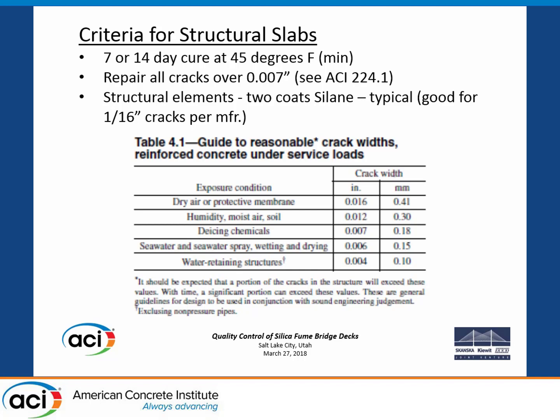So, can we just put silane on everything? The manufacturer says it's good for a 16th of an inch, 64 thousandths. If you look at ACI 224, de-icing salts, that's a roadway, right? 7 thousandths fits right in the scenario of ACI. If it's over 7 thousandths, it means bad crack.